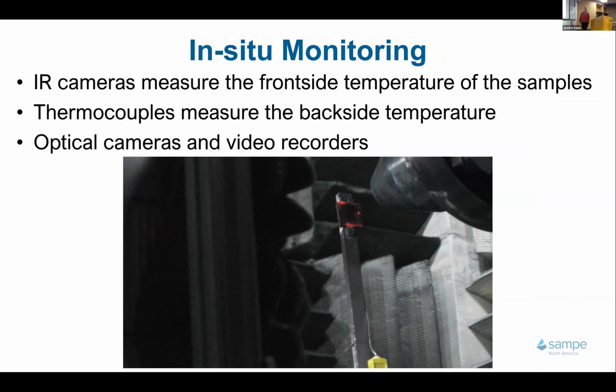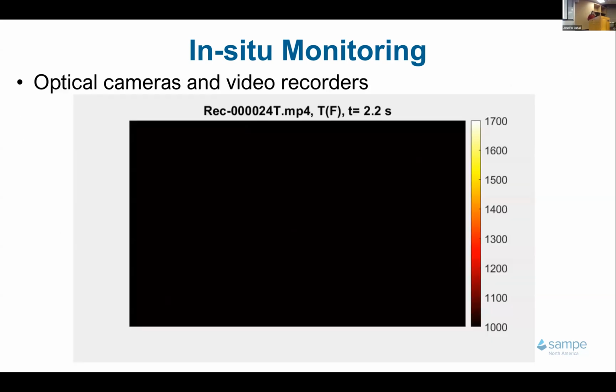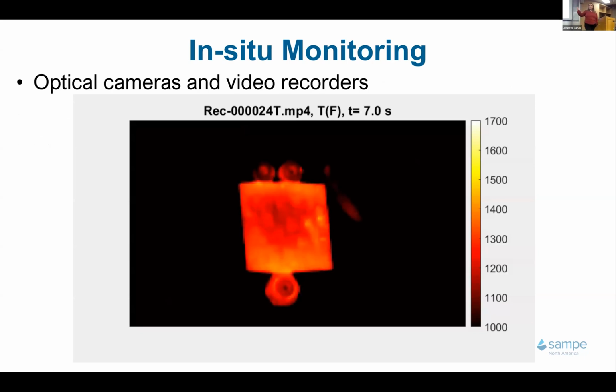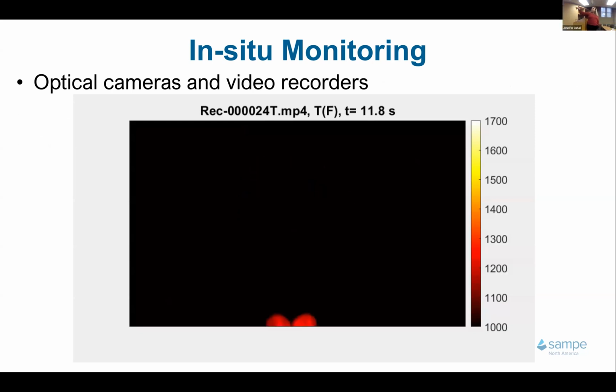Here's our poor little sample getting hot. Make sure this was muted. This was very loud. And then it drops away. So the thermocouples measure the backside temperature, and optical cameras and video recorders and the IR camera measure the front side temperature. Here's the video, probably from the IR front side camera. You can see we could actually track the exact temperature of the front.